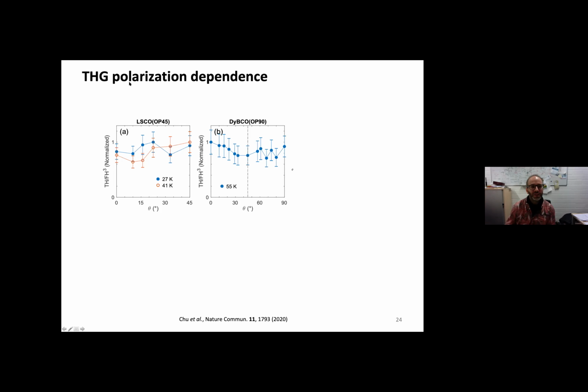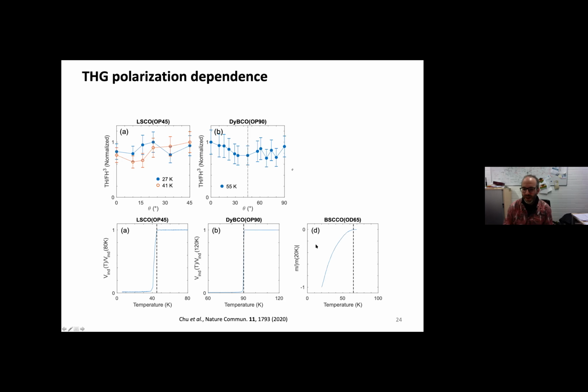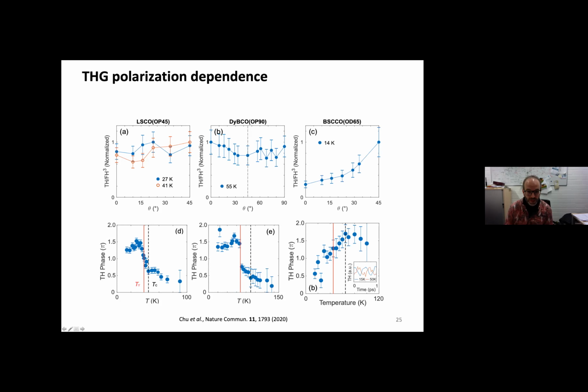And for this, we have also now performed a full polarization dependence of this state. And then you see in this LSCO and DyBCO, in principle, in these systems, we have no polarization dependence of the THG response, which is a strong fingerprint for Higgs response, because if this would be a current, this current has to obey the symmetry of the crystal, and that should have a very strong dependency on the polarization of this state. For example, if you have a very bad superconductor where you have a lot of hot quasi-particles in the system, then indeed you find these strong dependencies on the polarization state of a system. And then also this whole phase jump phenomenon basically disappears, or here you really see now a phase jump in the opposite direction due to a coupling with plasmons in the system.